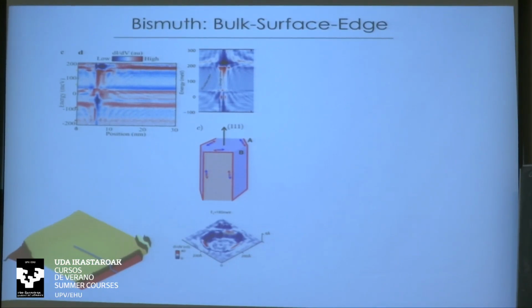And now let me switch to talk a bit about the topological properties of bismuth as we understand them. Perhaps the latest evolution in that is its characterization as a possible higher order topological insulator, which means that it's an insulator topologically classified in the 3D bulk, but its surface topological effect happens 1 dimension, 2 dimensions below the bulk classified band.